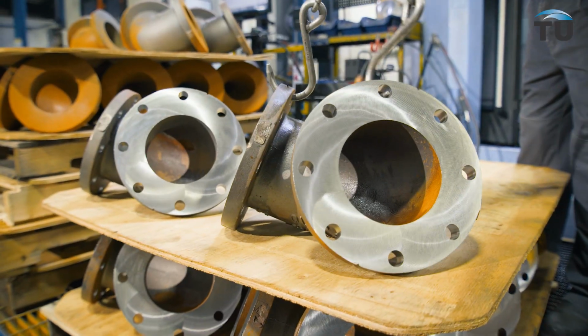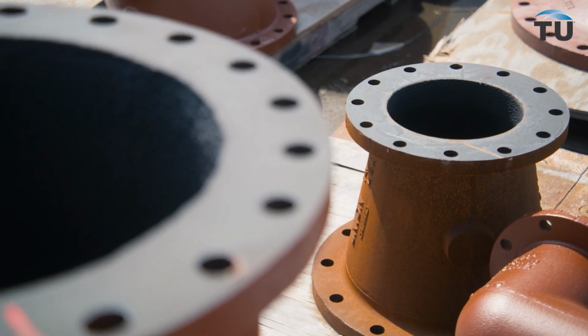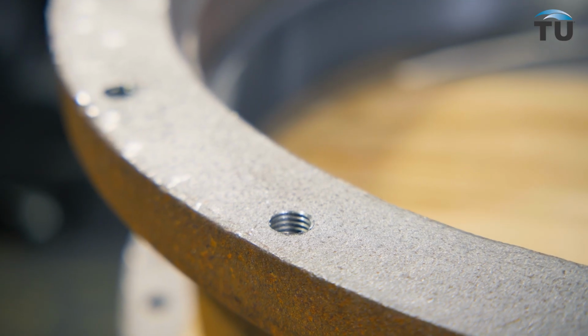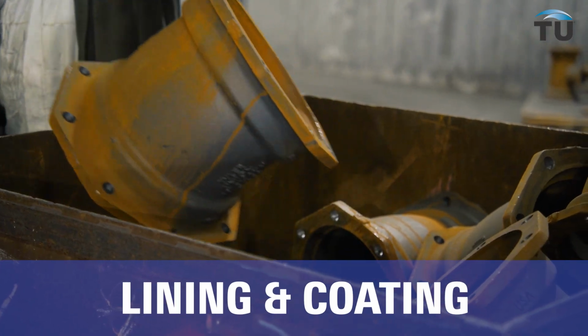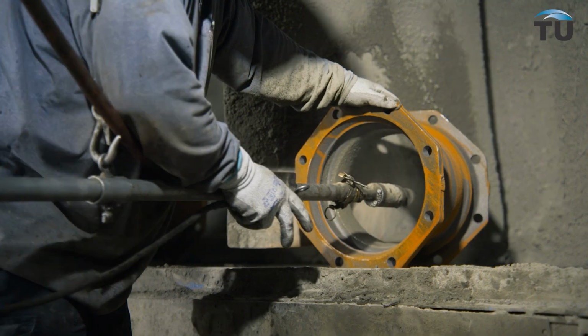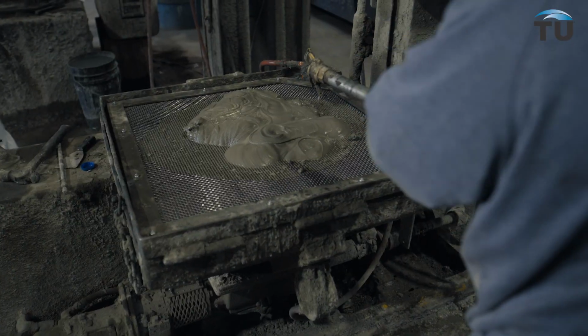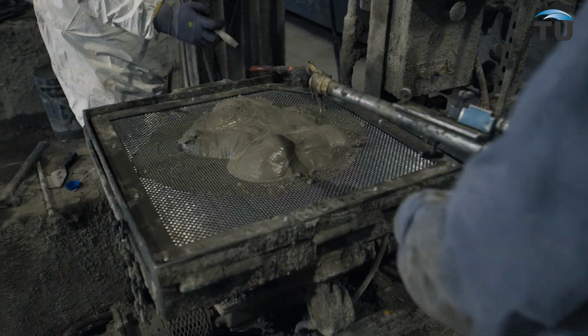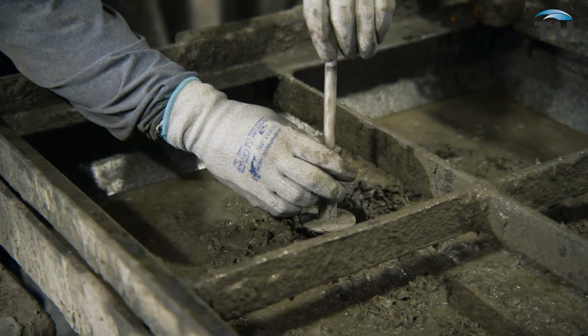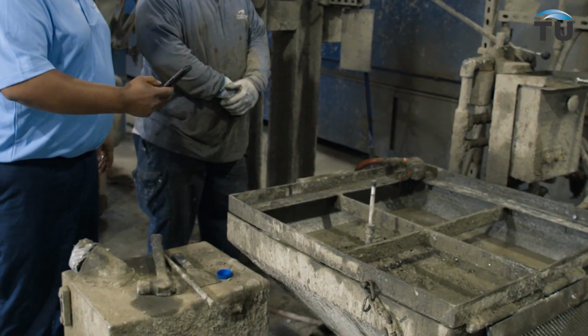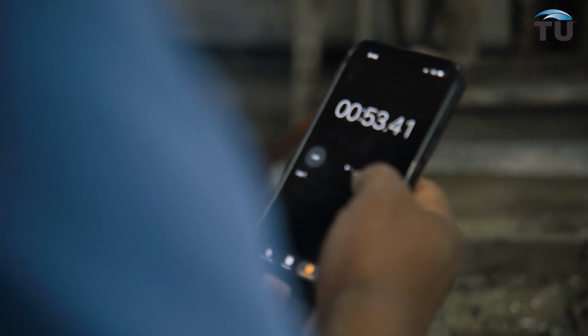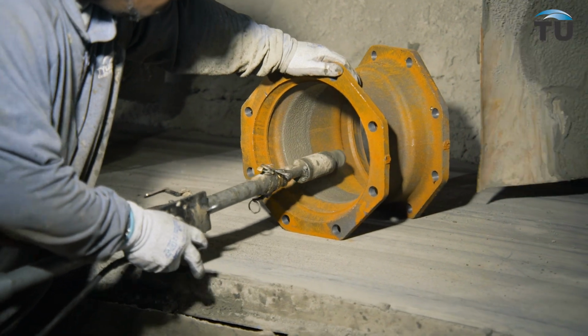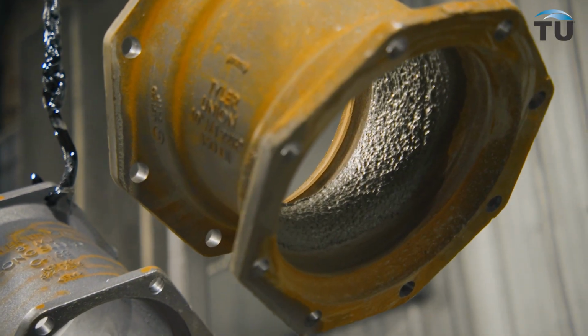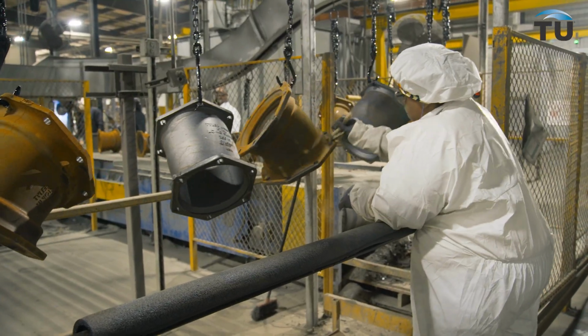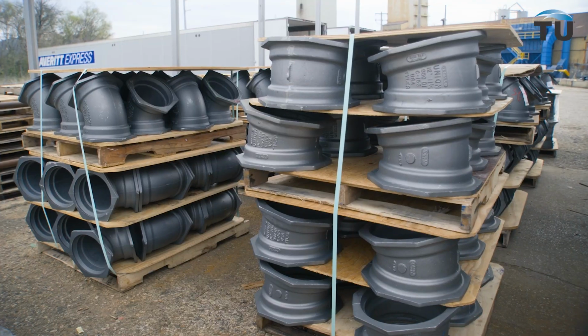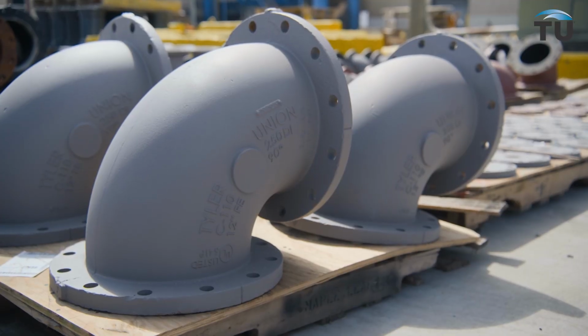All Tyler Union flange fittings are faced per AWWA standards, and drilling is inspected to ensure bolt holes are drilled through. After fittings receive final finishing, they are cement lined in accordance with AWWA C104. The cement is mixed using clean potable water and sand that meets NSF and Safe Drinking Water Act requirements. The viscosity of the cement is tested routinely to ensure proper flowability and texture. This test is called a slump test. The cement is sprayed into the waterway of the casting using specialty equipment. Any raised areas of cement are smoothed by brushing, and any excess cement in the gasket area of the casting is removed. Fittings can also be ordered bare, where no internal lining is applied.